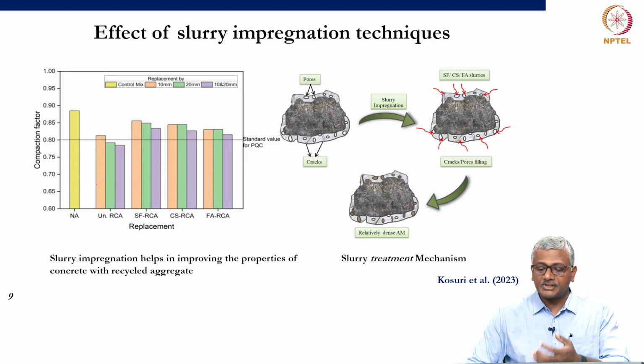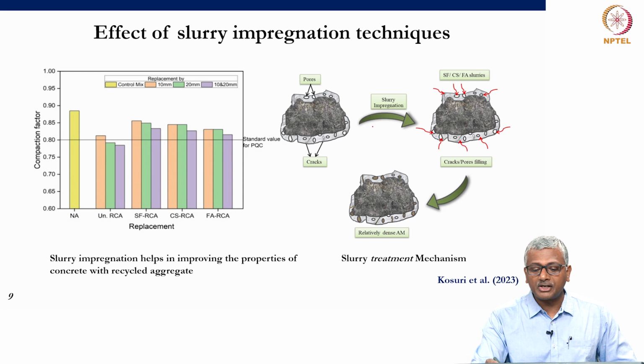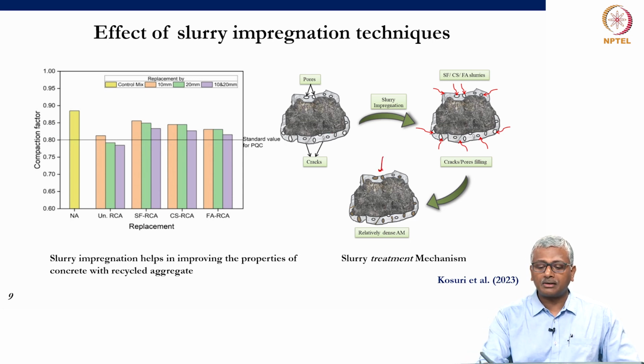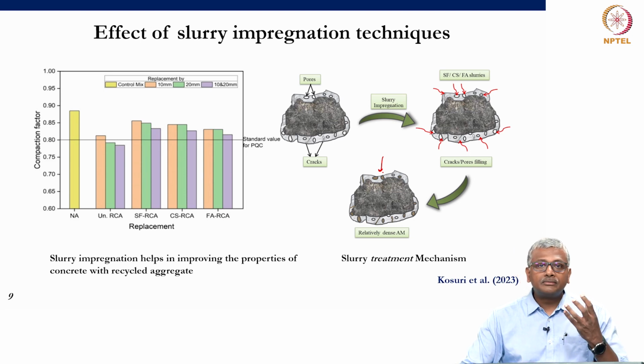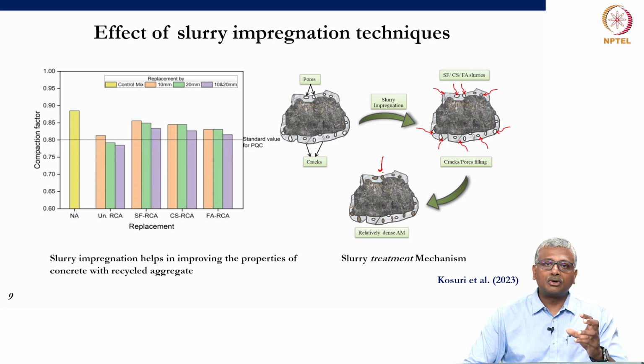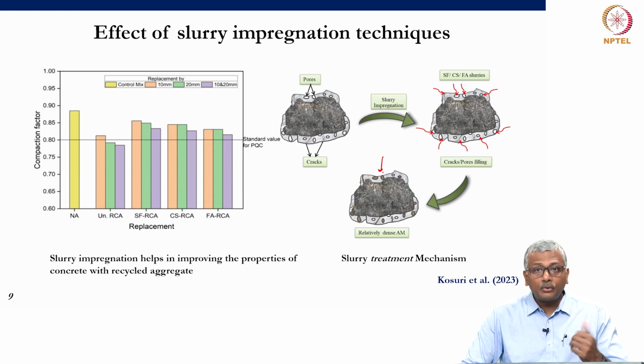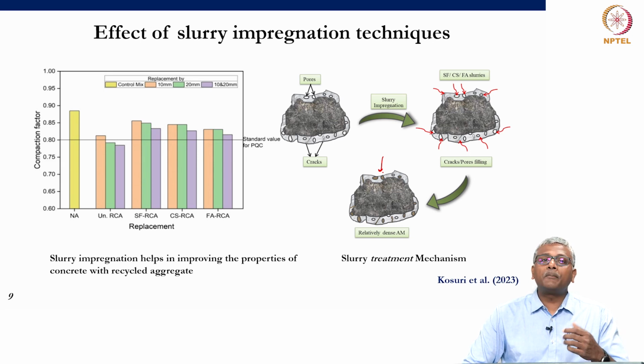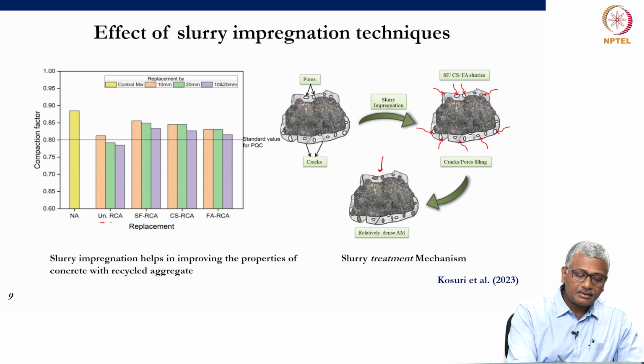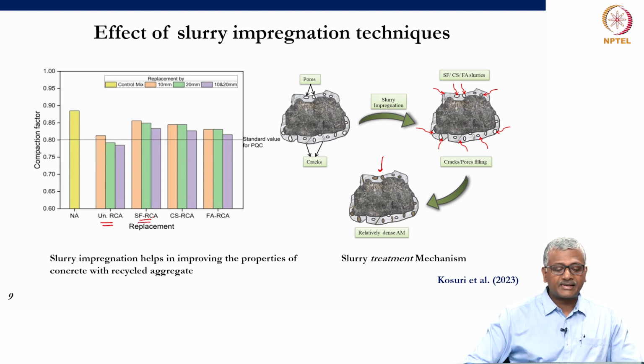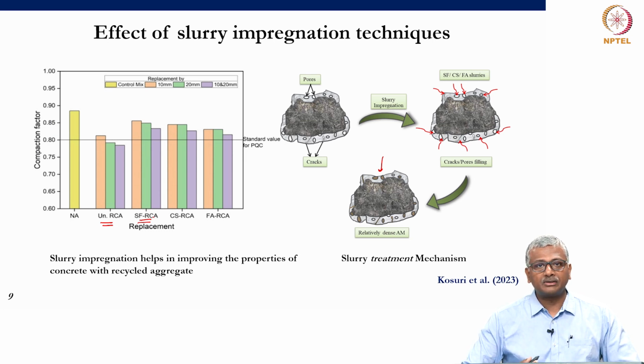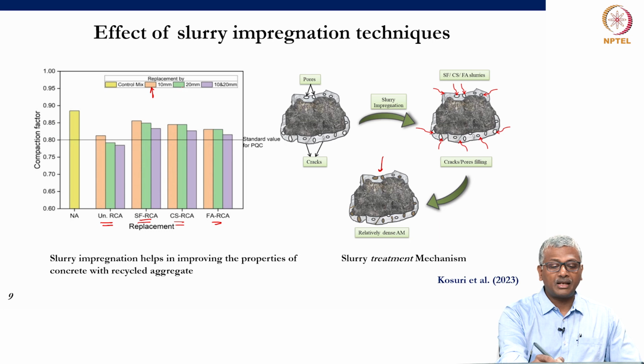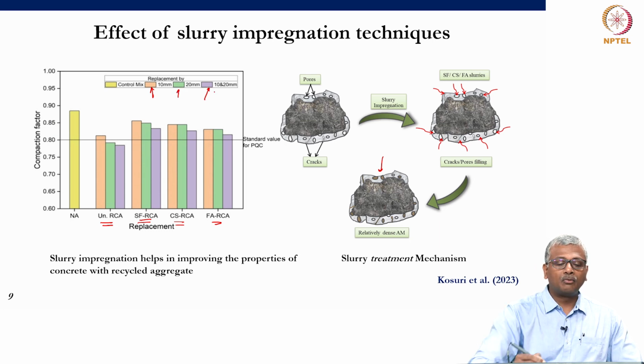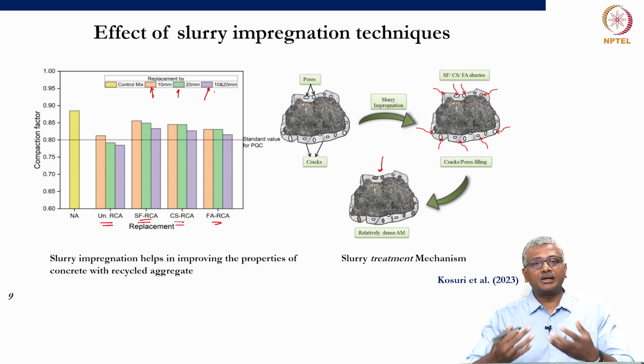Now, what happens when you do this? For instance, in one of the studies conducted at IIT Madras, slurry impregnation was done for recycled concrete aggregate, and we produced recycled concrete aggregate that was now more uniform with respect to its overall distribution of porosity, because most of the surface porosity was completely filled up by the impregnated material, right. So, now using this, we prepared concrete and tried to assess the compaction factor of this concrete, okay, for untreated recycled concrete aggregate, for recycled concrete aggregate where silica fume was used as the impregnation in the slurry, colloidal silica and fly ash. And we did the replacement for 10 mm aggregate separately, 20 mm aggregate separately, and in one more set of mixes we did both 10 and 20 mm aggregates which were impregnated with the slurry.